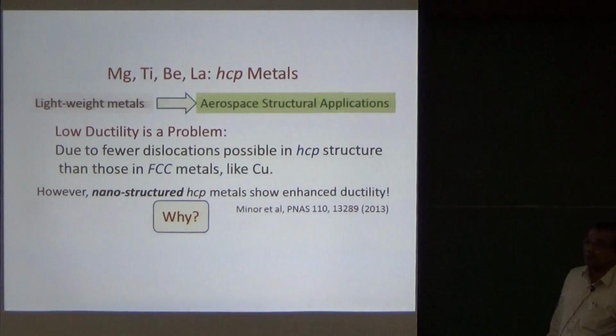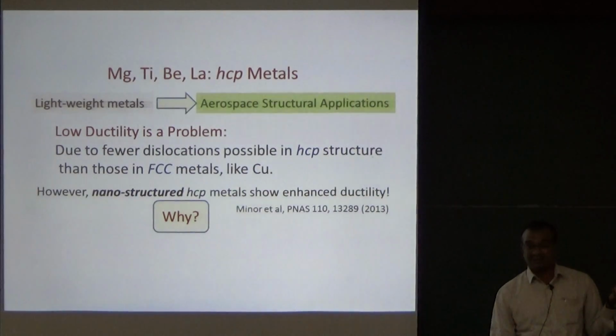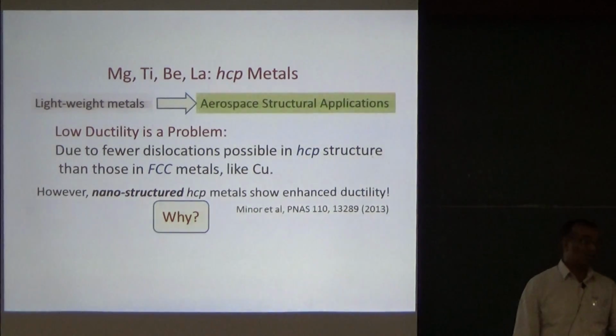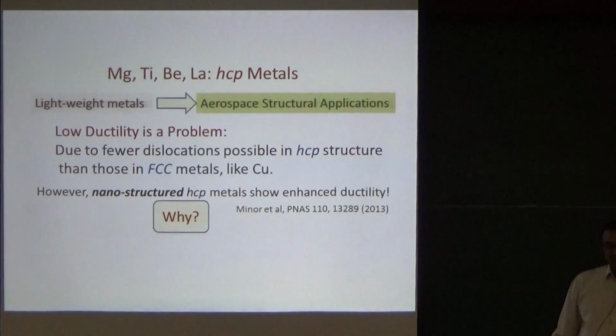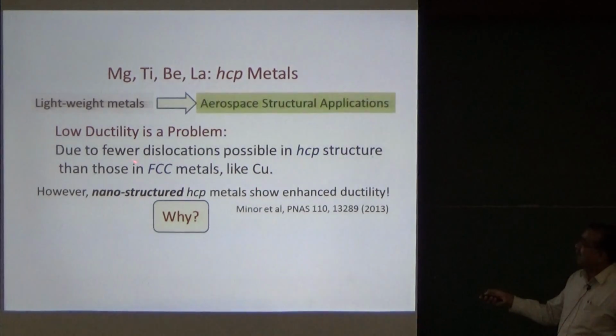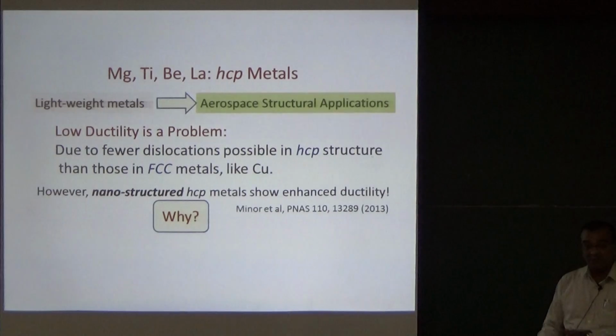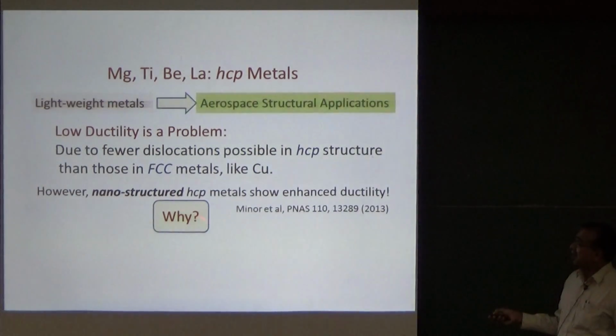is the fact that the HCP structure has two atoms in its primitive unit cell, okay, as opposed to FCC or BCC, which have only one atom in the unit cell. And the symmetry does not permit it to have enough dislocation systems which will give you plastic flow in a material in an easy way. However, nanostructured HCP metals show enhanced ductility, as was shown in this paper. And the question we asked is why?